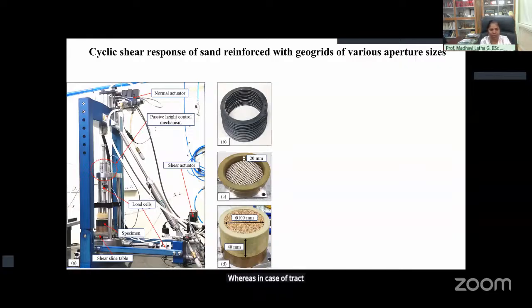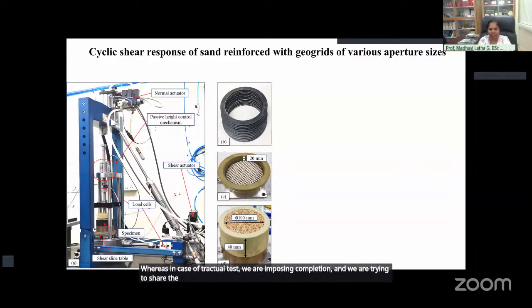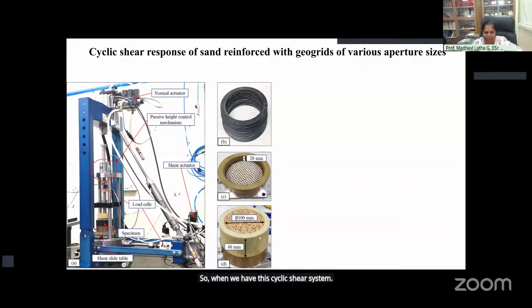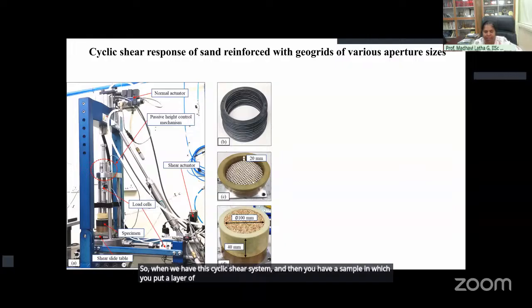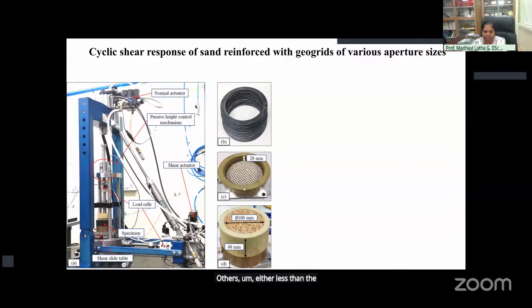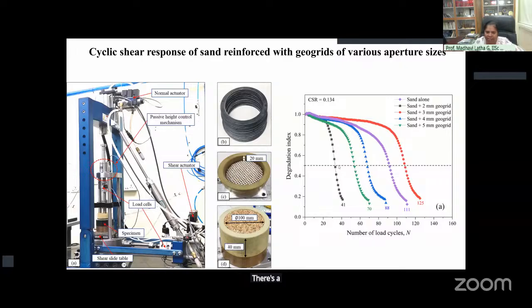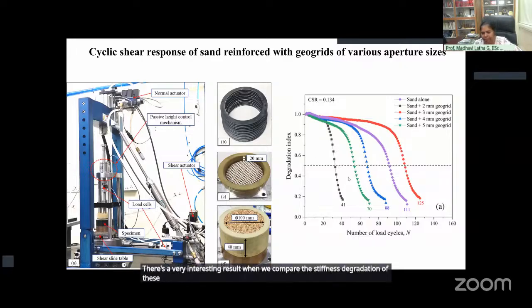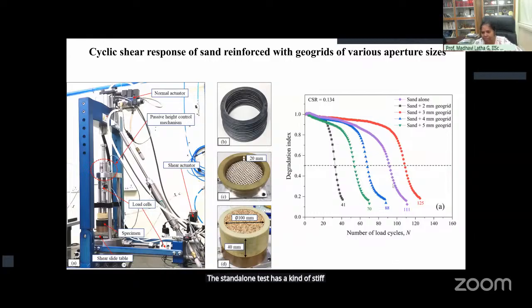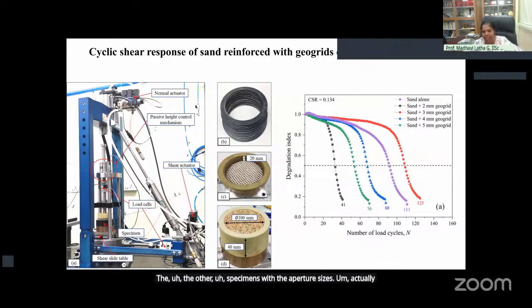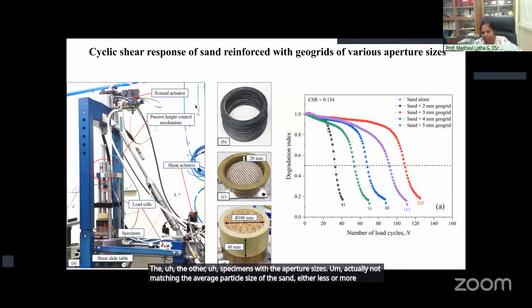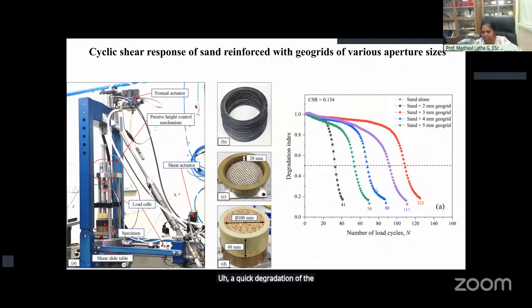Whereas in the case of the triaxial test, we are imposing compression and we are trying to shear the specimens. So when we have the cyclic shear system, you have a sample in which you put a layer of geogrid at the center with different aperture shapes, one matching exactly with the average particle size of the sand, others either less than or higher than the average particle size. And there's a very interesting result when we compare the stiffness degradation of these materials. The sand-alone test has a kind of stiffness degradation shown here. The other specimens with aperture sizes not matching the average particle size of the sand, either less or more, all have shown a quick degradation of the stiffness, whereas the system which has the exact aperture size as the average particle size showed very slow stiffness degradation.